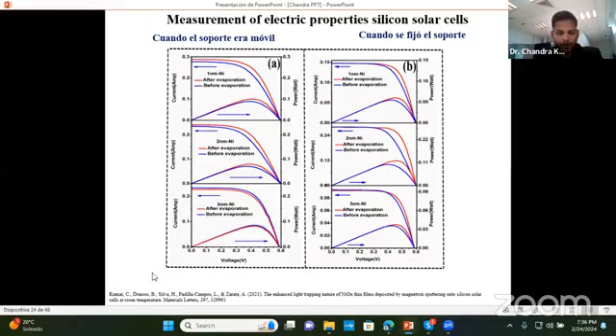The first result which we have reported, and this paper was also published in 2021, is the enhanced light trapping nature of NiOx thin film deposited by magnetron sputtering on silicon solar cell. We used two different conditions when depositing through magnetron sputtering. In one, the supporting holder in sputtering is kept in moving mode, and in the second I keep it fixed. When it was moving, we got a homogeneous or uniform film. But when we keep it fixed, we got a lot of defects, a lot of disorderness or non-homogeneous structure, but that was better for our purpose.